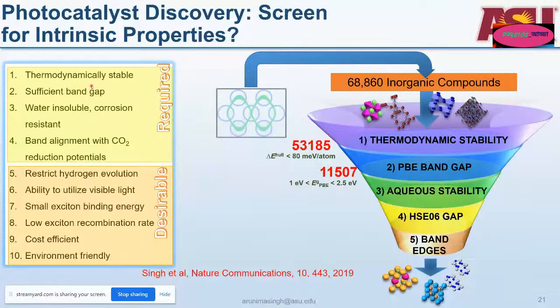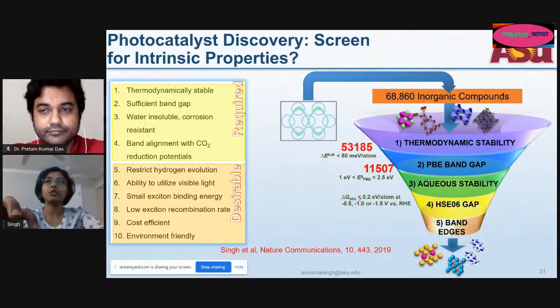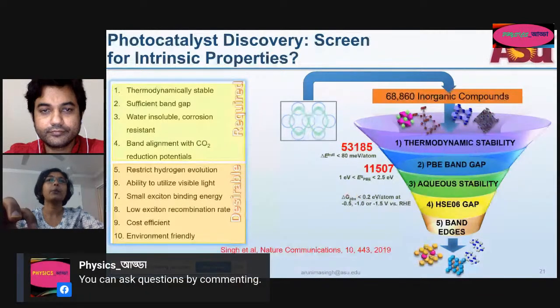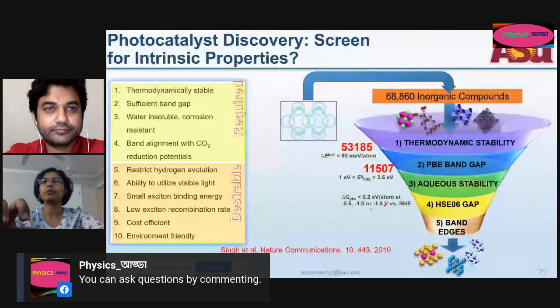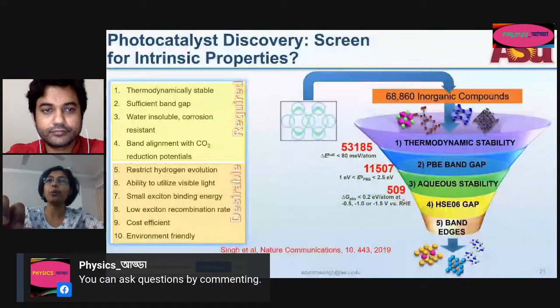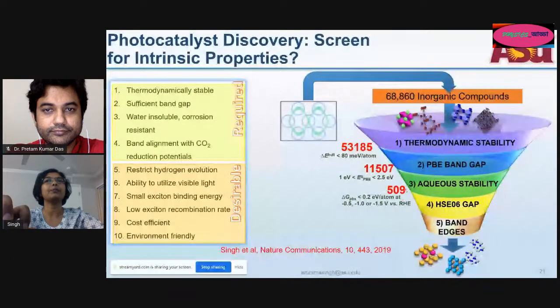All right, so let's come back to CO2 reduction photocatalysts. And we were stuck at this point where we did not know how to determine the aqueous stability. This aqueous stability, now that we have a quantitative measure because of electrochemical stability maps, we looked at the delta G with respect to Pourbaix stable phases, and we set it to 0.2 eV per atom at the reduction potentials where CO2 reduction happens. And we found that there were only 500 materials amongst the 11,000 which satisfied this. This really highlights the importance of looking at the aqueous stability.